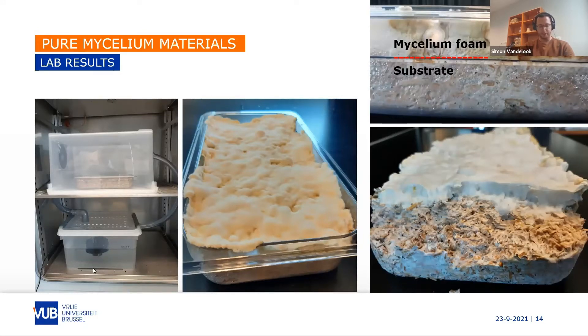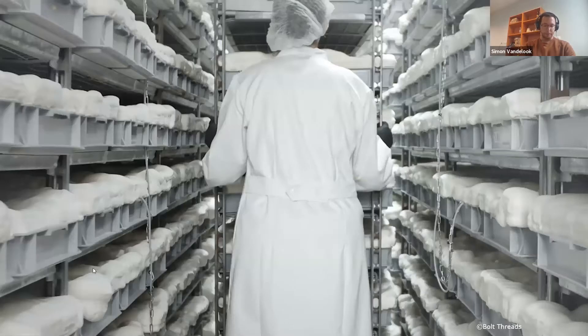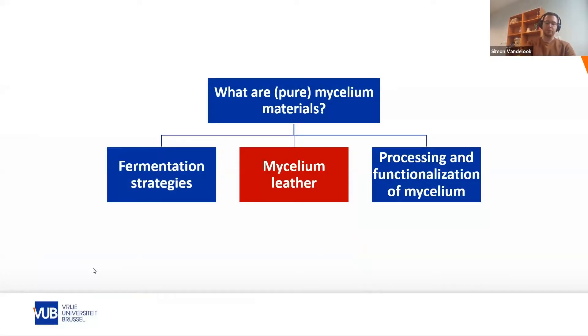Here are some of my own results for growing this foam-like phenotype in a very rudimentary DIY setup, where I managed to achieve about one to two centimeters of aerial hyphal growth. This setup is located inside a CO2 incubator and is composed of two boxes connected by a hose with a fan circulating the mist. When you fully optimize this setup it is possible to achieve big volumes of foam and also vertical farming, which is very efficient.